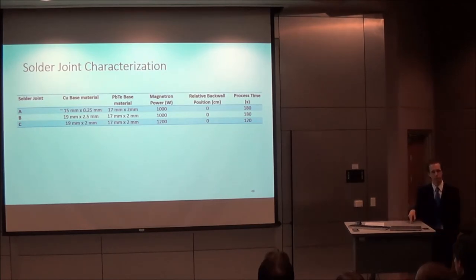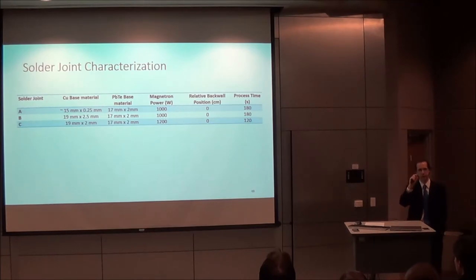The numerical model was adjusted and run at a higher power and over that 3-minute time span. And then the temperature versus time was evaluated and I picked a point that was enough after the melting point of the solder had been reached, according to the model, that I would be fairly confident that it would join using that time and that power in the actual apparatus. And sure enough, it was successful.